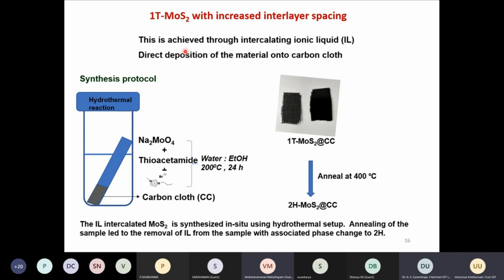Our idea is to achieve this 1T phase. There are reports that small molecule intercalation into the MoS2 layers, in between the layers, can increase the distance and that creates the 1T phase in the material. So we thought, why don't we have an ionic liquid inside the material, and we synthesized this using a simple hydrothermal setup where we have taken sodium molybdate and thioacetamide as the sulfur source, and a simple bromine-based ionic liquid, and we tried to directly deposit the material on the carbon cloth. The reason is that if you prepare it and then later deposit it, you need some kind of binder, which will create some resistance.